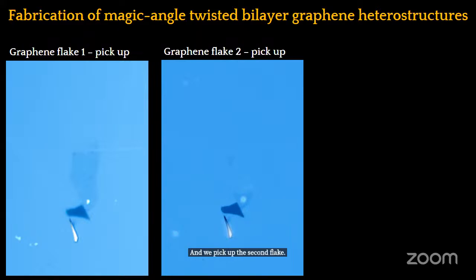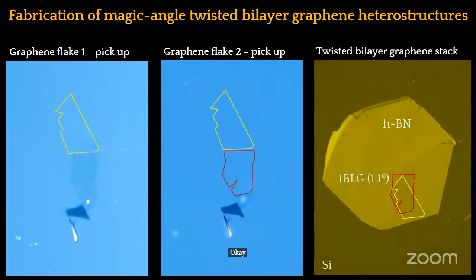The angle or misorientation has been introduced in between these two steps, okay? So this is the result. This is one of our first twisted bilayer graphene stacks that we have on top of the boron nitride substrates, etc. And in principle, theoretically, they show a mismatch of 1.1 degrees.